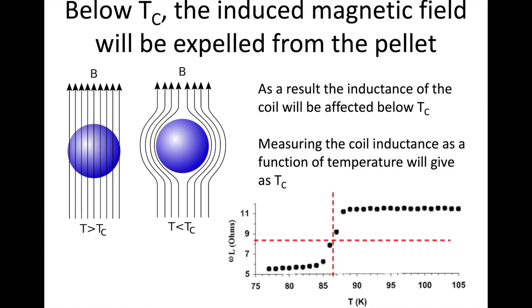When we run this experiment, we look at inductance in the coil as a function of temperature. Above the critical temperature, we're going to have a fixed or nearly fixed level of inductance because nothing is happening. Then we reach a point where the inductance changes. Below the critical temperature, it's also at a relatively fixed value of inductance. That transition region is our critical temperature. The common way to measure this is to take the inductance above and below, divide by two to get a midpoint, and find the temperature at that midpoint of the inflection — that is what we term the critical temperature.